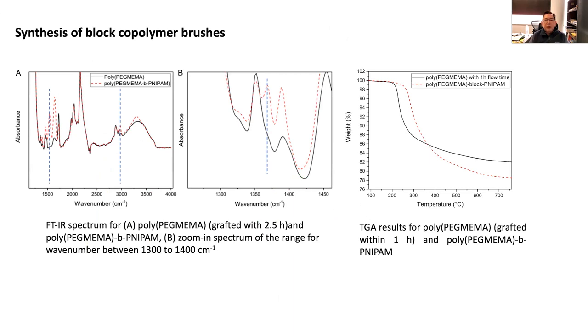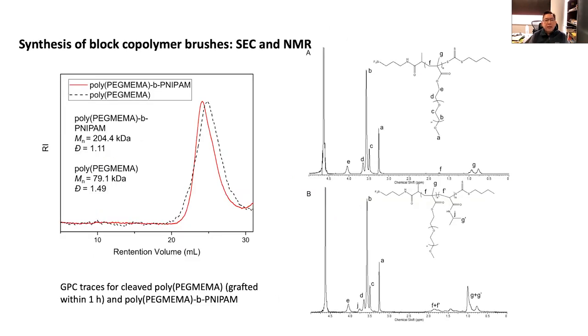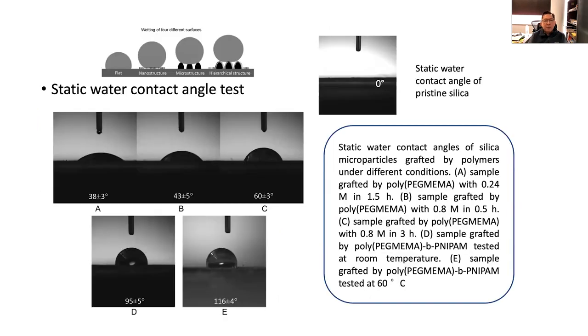And then we characterize this block copolymer based on IR as well as TGA. And here you can see the corresponding molecular weight after degrafting from the surface, showing the difference between a homopolymer and a block copolymer. And the surface has been modified, as shown by the change in the wetting behavior.